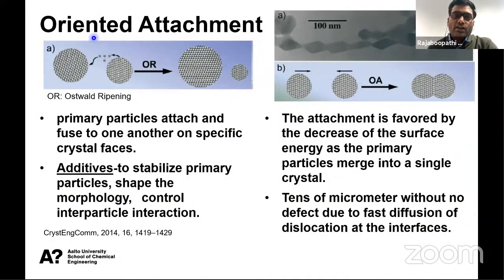Okay, so what is oriented attachment in non-classical crystallization? Before we see what oriented attachment is, we should know what Ostwald ripening is. Ostwald ripening means after forming the supersaturated solution, the nucleus size is not so uniform. Sometimes it may be large or small. If it cannot reach the critical radius, it will dissolve and attach to the large size particle. The small particle cannot grow further because it cannot reach the critical radius due to surface free energy. So it will dissolve and attach to the large size particle. In another way, we can say the big fish eats the small fish to grow further. So we can say it is Ostwald ripening.